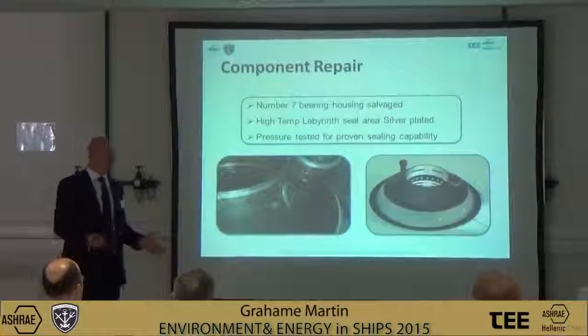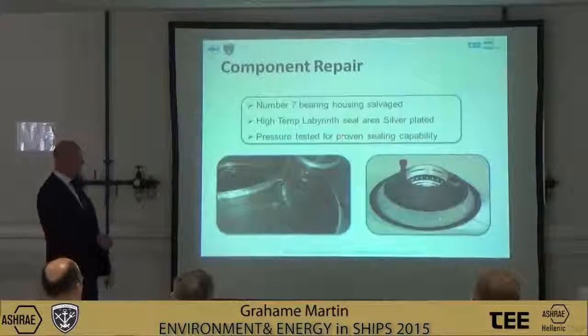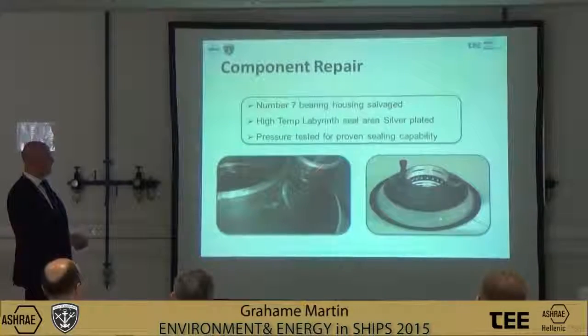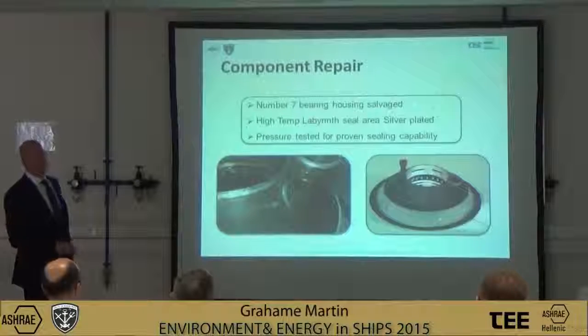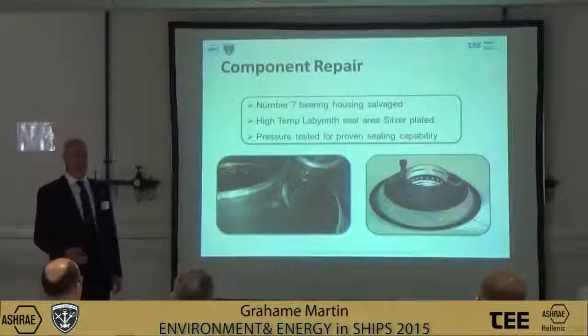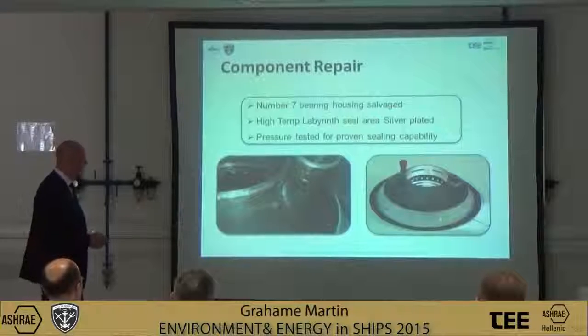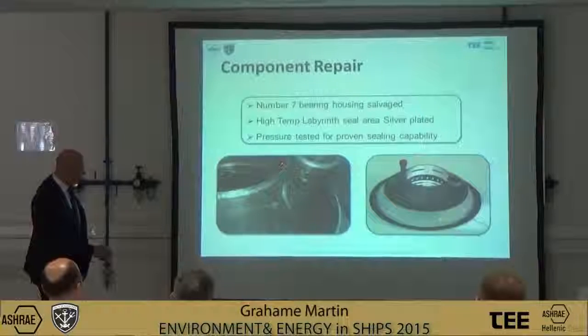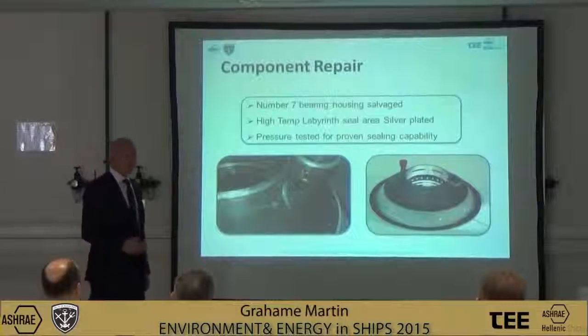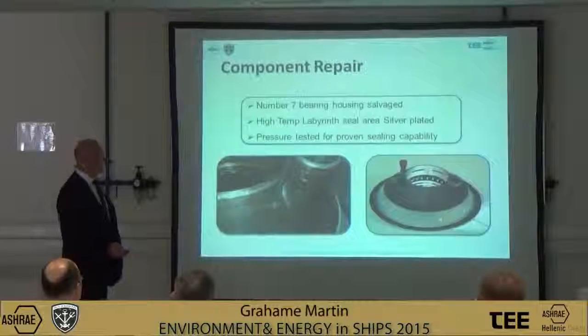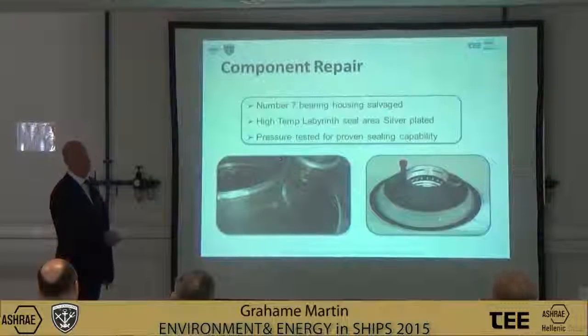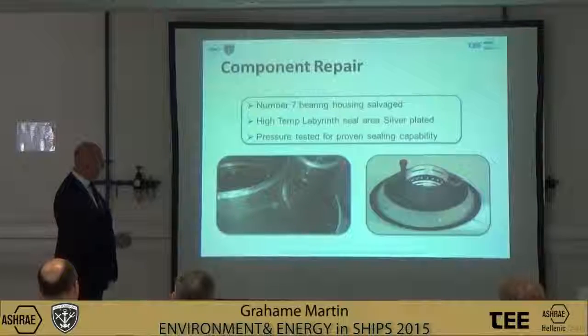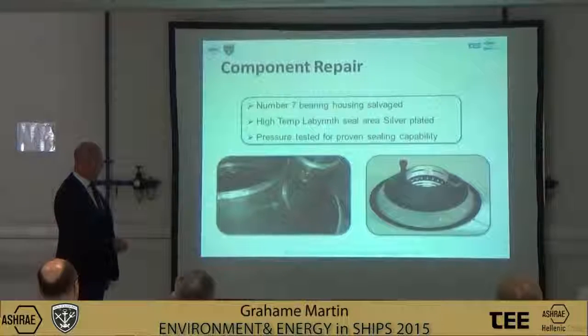This is another repair scheme that we've developed. Again, it surrounds the Olympus, and hopefully you can see this location here. This elbow here is the air feed for the sealing and cooling air for the number 7 bearing on an Olympus. And what traditionally happens is in this location here, which is the static labyrinth seal for the forward first stage turbine labyrinth seal, we get a degradation of the actual seal itself. But further on this unit, we have also developed a crack in this area.